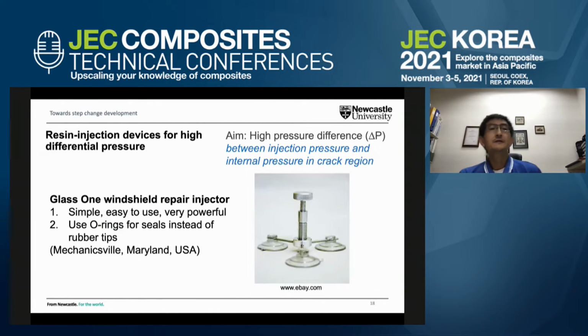So the first area for dealing with resin injection repair is the resin injection device, and we want to achieve high pressure. Well, also because as the ingredients suggest, if you have high pressure, you could also have shorter time for the resin injection repair process to take place. And of course, that's good because it contributes to shorter turnaround time for the repair. And for the resin injection device, we take our motivation from the simple windshield repair injector that you find in a typical car garage.